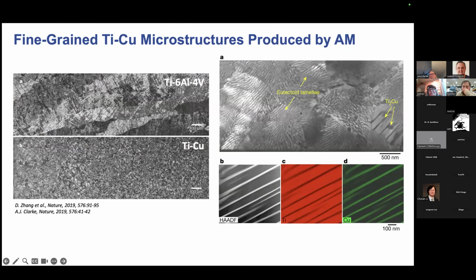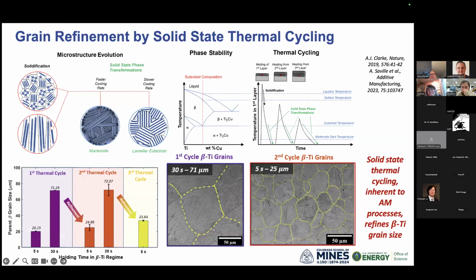What's neat about Ti-Cu (titanium copper) is that you actually form a eutectoid product in the solid state as well. And this is much like pearlite in steels. However, this eutectoid product in Ti-Cu is at the nanoscale. It's much, much finer, which is pretty interesting.